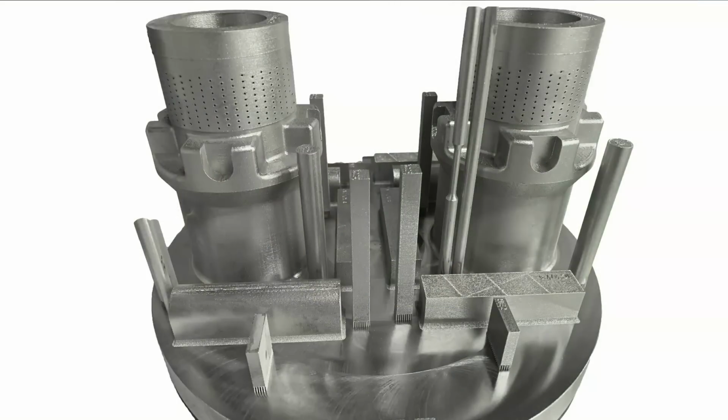Exactly. And so when you're looking at the traditional market and everybody running their machine slightly different than the next, the material properties can vary drastically. And if the feeds and speeds of the laser and the toolpath are all different, you have to focus on ensuring that they can meet what your standards might be. And where you draw that line in the sand is what the industry calls witness coupons. Witness coupons are usually coupons that you print in your build at the same time as your part that you can then go test to ensure that your material is coming out the way that you expect it to be.